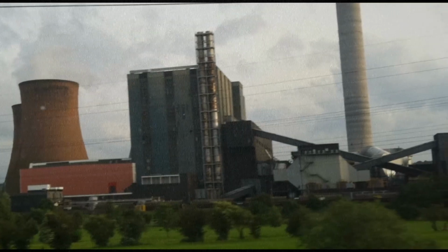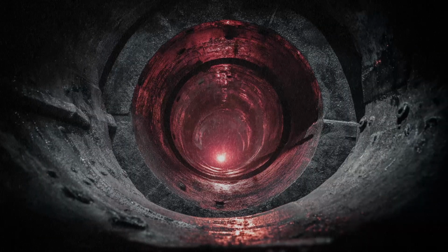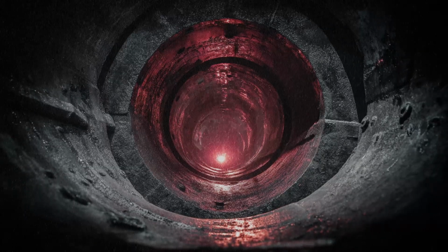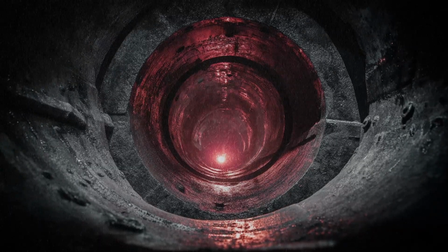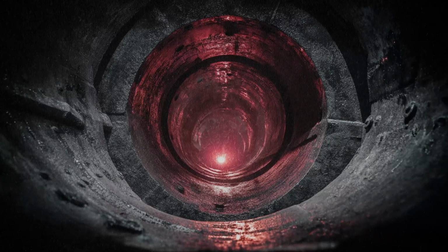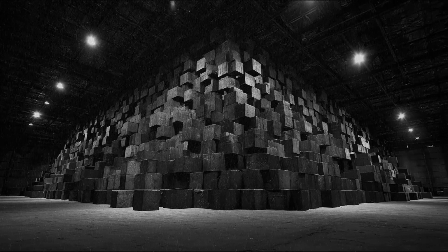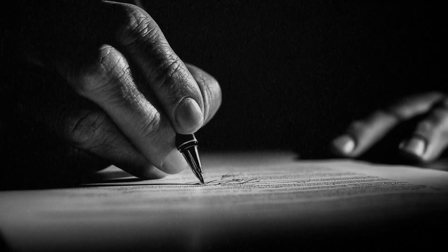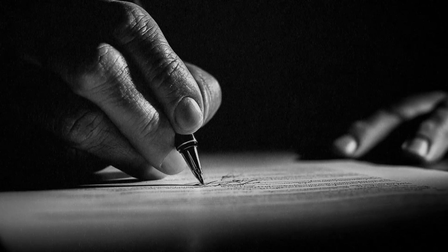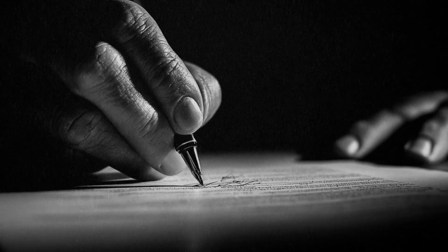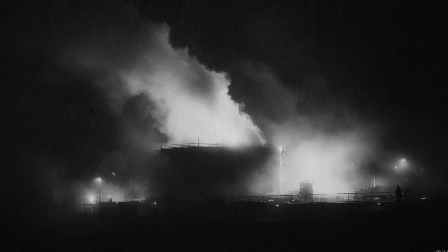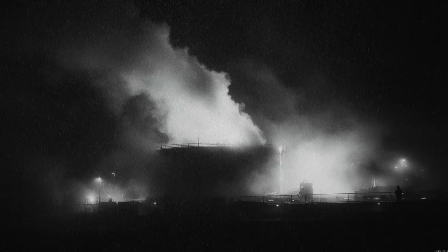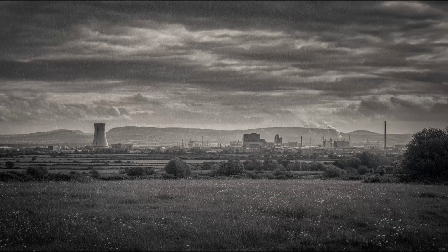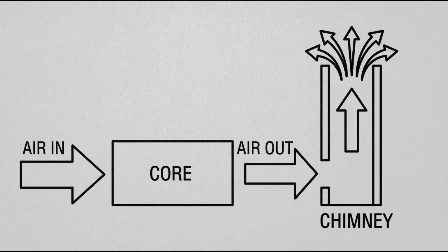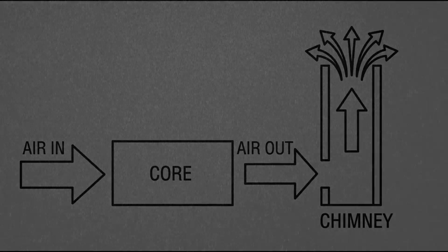The reactor still stands at Sellafield. Inside it, 15 tons of fused uranium remain, too radioactive to approach, too entangled with the graphite to extract. The graphite still holds Wigner energy. The water used to extinguish the fire may have created uranium hydride, a compound that ignites on contact with air. Decommissioning is expected to take until 2120 at a cost exceeding £120 billion. All within protocol, all signed off. And the air still moves through Sellafield, as it always has.